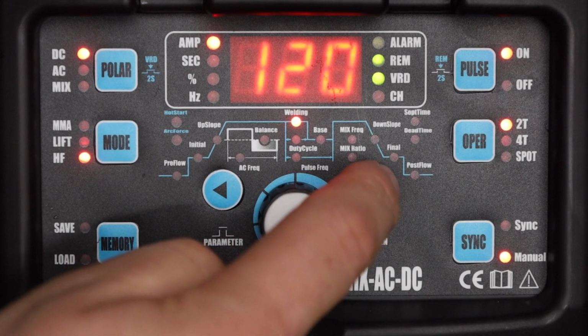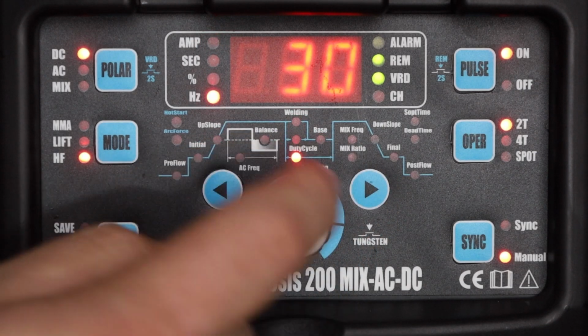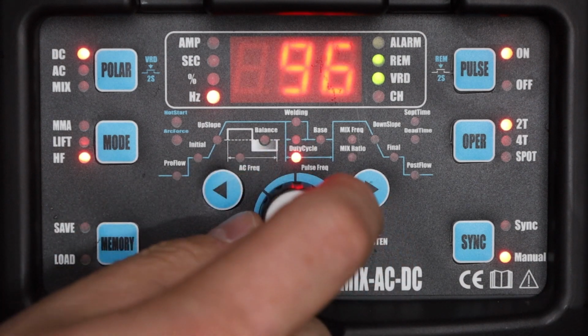Notice how pulsing at this frequency is very similar to welding just with straight current, except a slightly more focused arc. The 30 Hz frequency can be bothersome for some operators, so I'll go ahead and turn it up to 100 Hz and we'll take a look at that. Once again, it's very similar, except the arc is just even more focused, and this can be very useful for thinner material or when you're welding near the edge of your material.